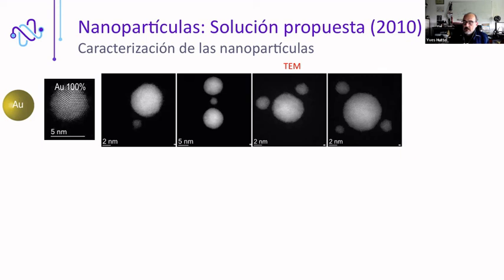Regarding the yield, the first step is when you deposit the nanoparticles on a surface. The nanoparticles have a given sticking coefficient on the surface. And the sticking coefficient is dependent on the material of the nanoparticle and the material of the surface. And it's amazing because you can have differences of 3 or 2 orders of magnitude with the same nanoparticle, gold nanoparticle, for example, on different substrates. So the time you will need to cover the whole surface with one layer of nanoparticles will depend pretty much on the surface. But once you have created this first layer, you have gold nanoparticles that will land on gold nanoparticles, and the sticking coefficient will be 1.